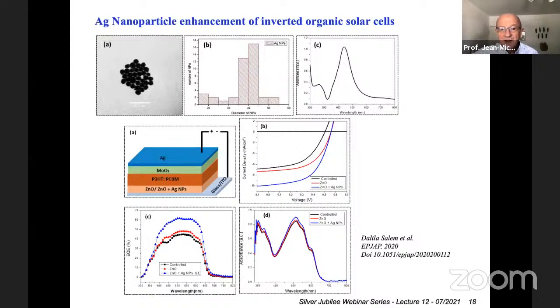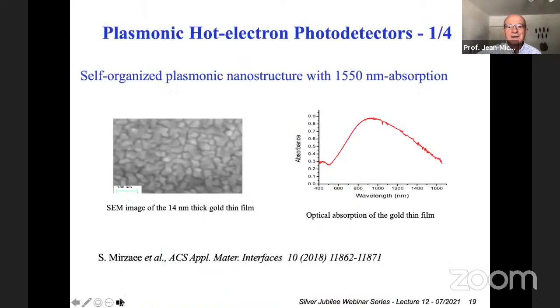But we can design other photodetectors with these things, because actually we can use, for instance, in that case, a layer of nanoparticles which were deposited on ITO. In that case, it's a plain gold film that was deposited under a vacuum, but it's not exactly a plain gold film. It's deposited under a vacuum onto a hot substrate. The hot substrate is glass with ITO heated at about 150 Celsius.